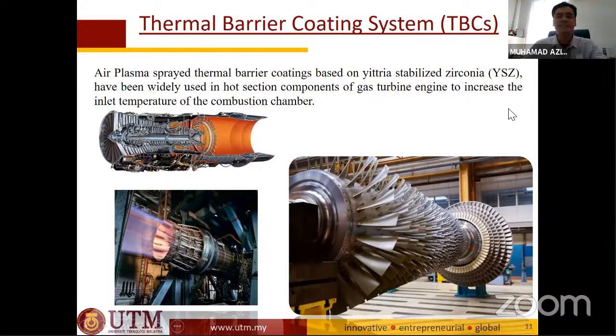Okay, so with this very high temperature at the combustion section, there is a problem for the materials or the metals, because metal will experience creep or expansion of the dimension due to the heat, especially if you're talking about aviation. You're talking about an engine that works for hours, hundreds of hours, thousands of hours. So therefore, there is a need for each of these.